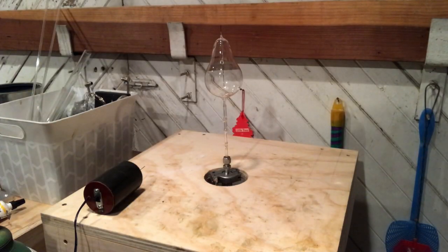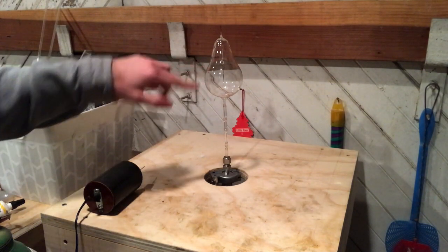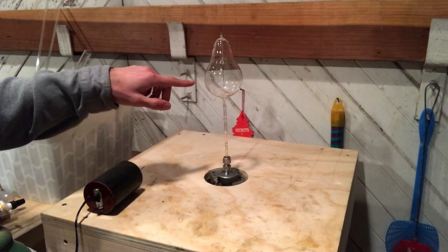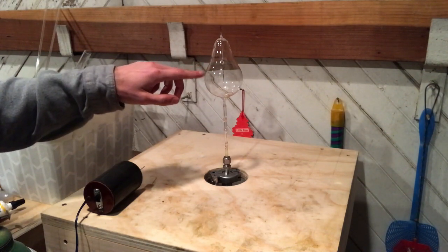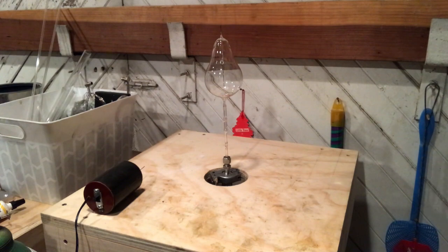And what we'll do is have this pumped down for maybe about 5 minutes without the bake-out oven on it just yet. And what we're going to do is hook up the diathermy machine to the lamp and physically drive out all the contaminants and water molecules found within the filament, as well as the inner wall of the glass. So by using these high frequency currents, we will be able to evacuate the lamp even further, as the bake-out oven cannot necessarily release all the contaminants found within the filament.